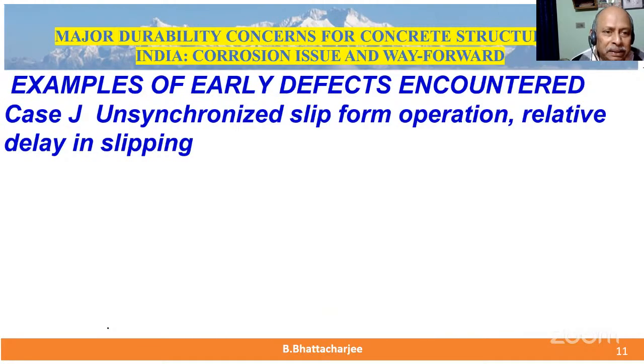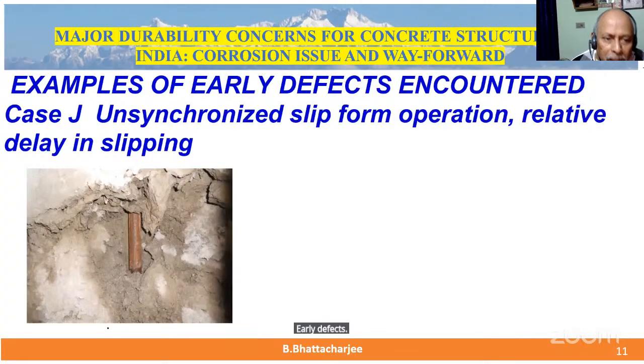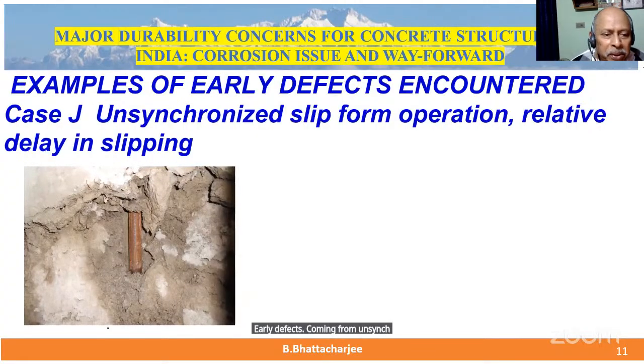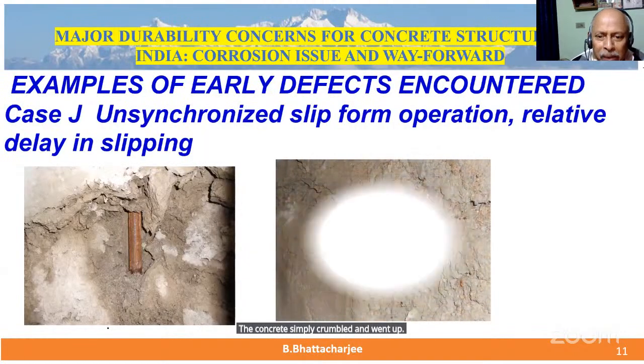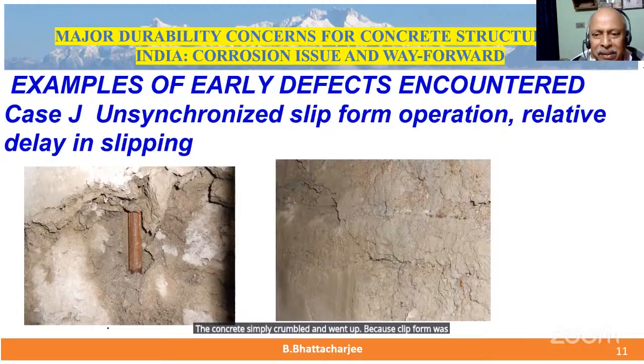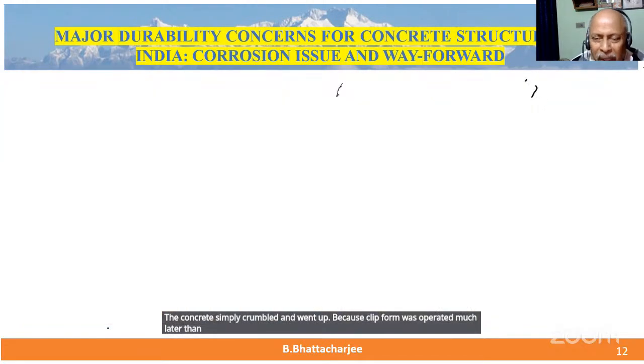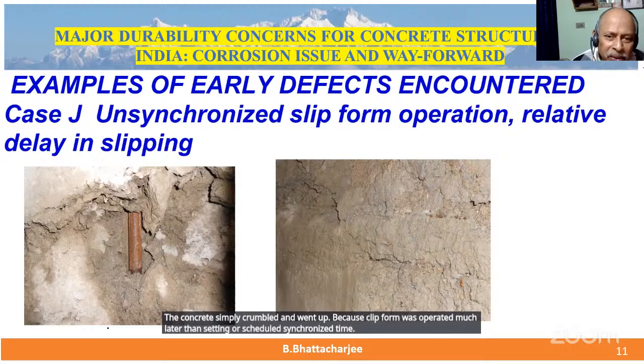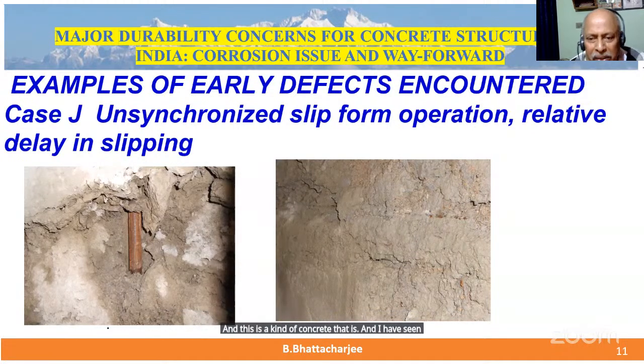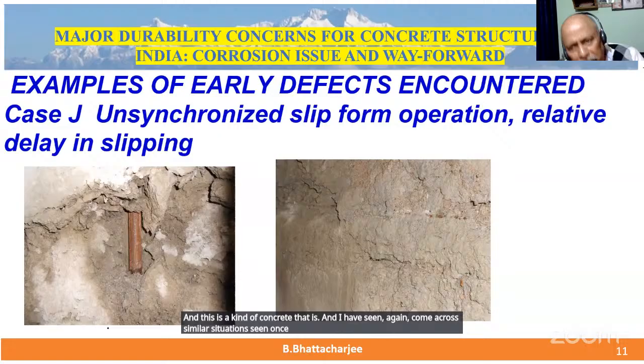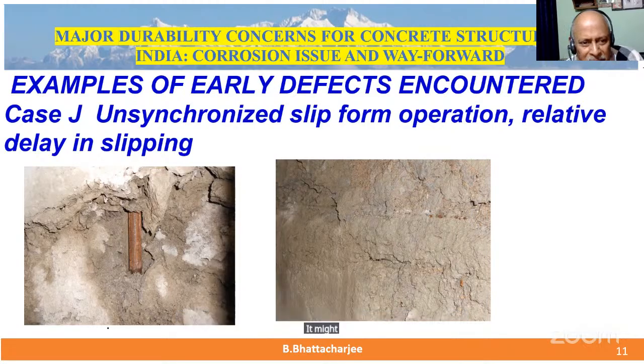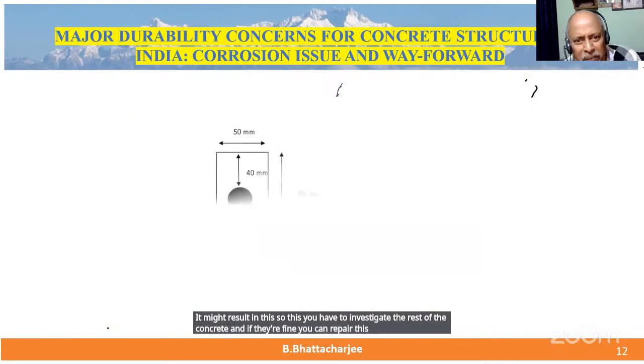Early defects coming from unsynchronized slip form operation. The concrete simply crumbled and went up because the slip form was operated much later than the setting or scheduled synchronized time. And this is the kind of concrete that you see. I have come across similar situations, seen once or twice, but reported a number of times. This is one thing, they have to synchronize it properly. If you don't do that, it might result in this. So you have to investigate the rest of the concrete, and if it is fine, you can repair this portion.